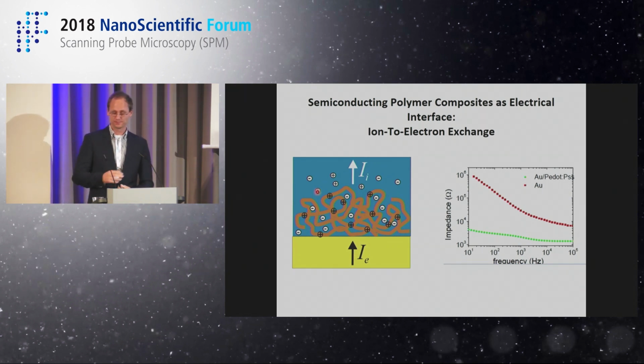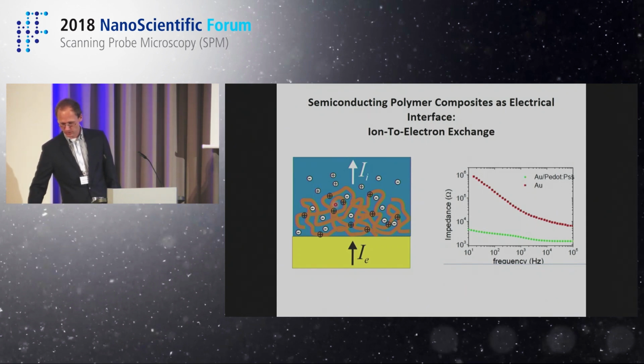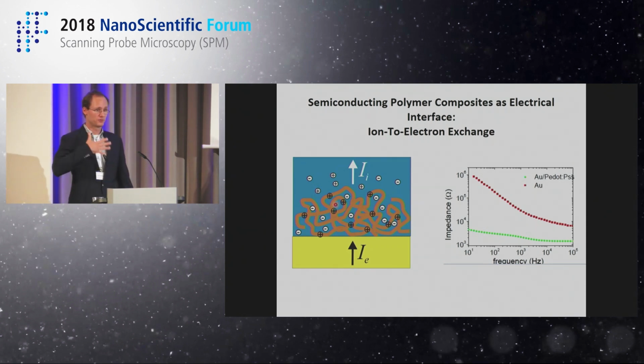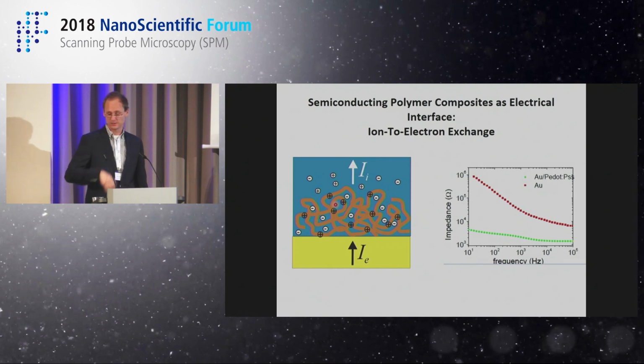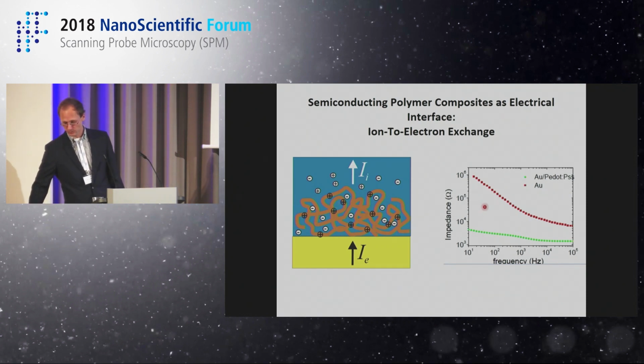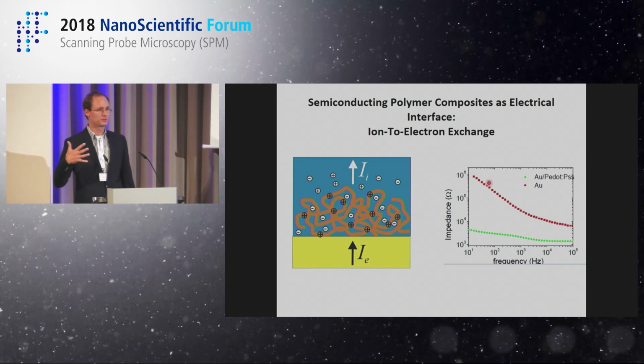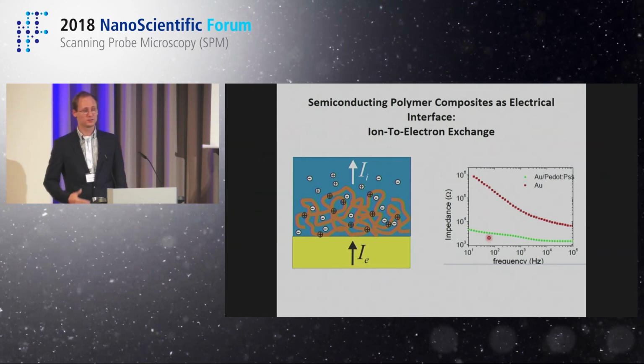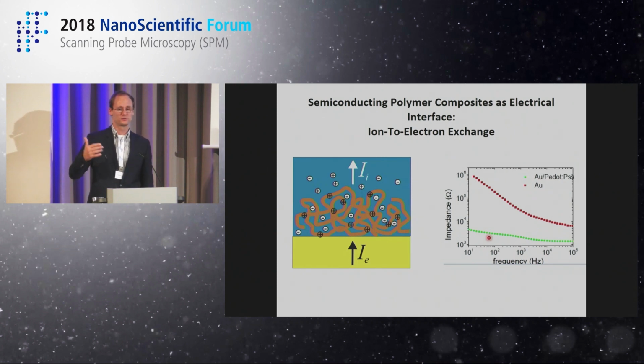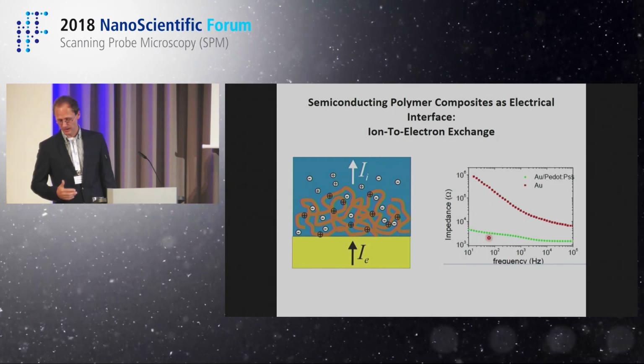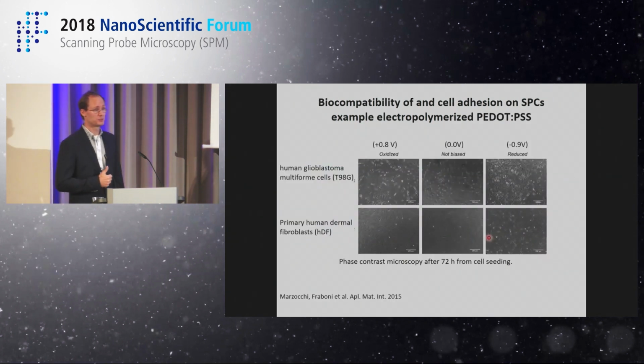Or for electronics, you would speak of a very low impedance if you think of an AC signal that has to traverse this interface. So if you do the impedance spectroscopy, if you have just a normal electrode, you can see here that, of course, at lower frequencies, you get very high impedances, and it will be difficult to transmit signals across this interface. Now, if you apply such a composite, you can see that you can drop it even orders of magnitude, meaning that you facilitate a lot the transmittance of information, and of course, that's very, very important if you have small signals. That's one reason why such materials could be of interest.